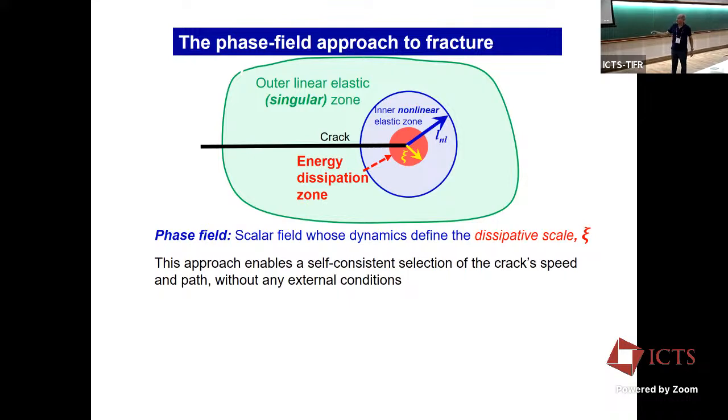Out here, it's just finite element using linear elasticity. So we're calculating all the fields. And now as you approach the nonlinear region, the idea is to insert a scalar field that behaves like the Landau equation, roughly, or Landau-Ginzburg equation.